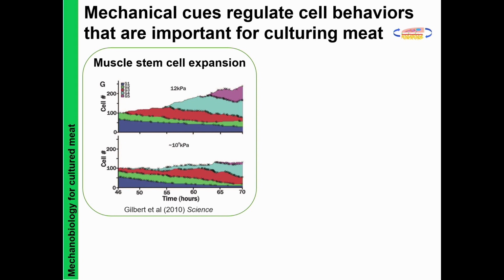So to give you a background of some of the key studies that have really motivated our work, this is a study from Penny Gilbert looking at the expansion of muscle stem cells, and she plated some of these muscle stem cells isolated from mice on more compliant PEG hydrogels. This is the modulus, 12 kilopascals, that just is a measure of the stiffness of that substrate, and compared to cells that are plated on a stiff petri dish. And you can see over time the expansion of the cells on the softer, more compliant hydrogel is higher than the cells on the stiffer substrate. So that's expansion, very important for cultured meat production.